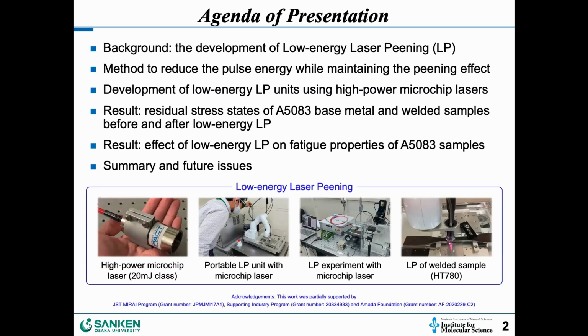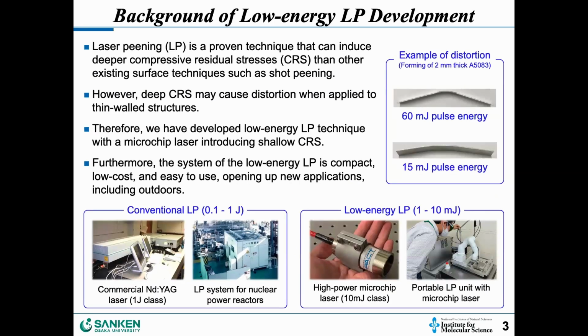And so we can apply such laser peening to welded material and confirm that it improves the fatigue strength. So today I would like to show the effect of laser peening on the aluminum alloy A5083. Usually, if we apply laser peening with high power, it bends like this. However, in our case, the laser energy is very small, for example, 10 millijoule or so, and it can prevent distortion.